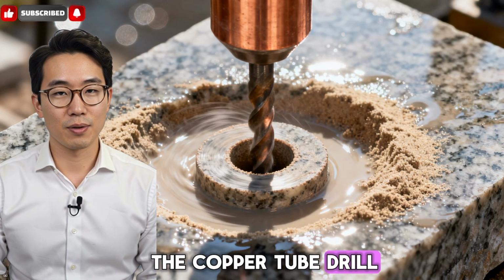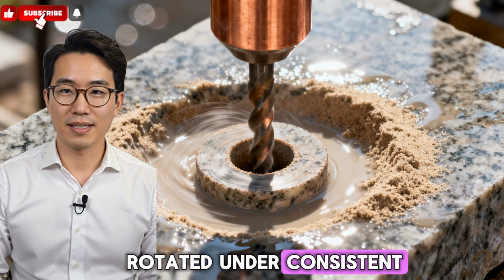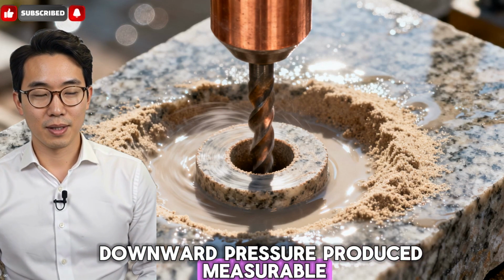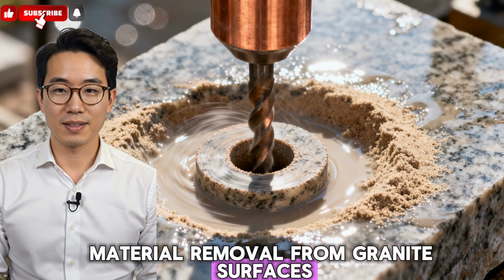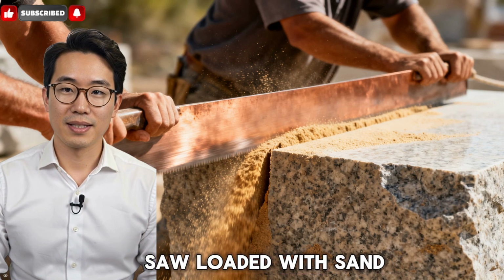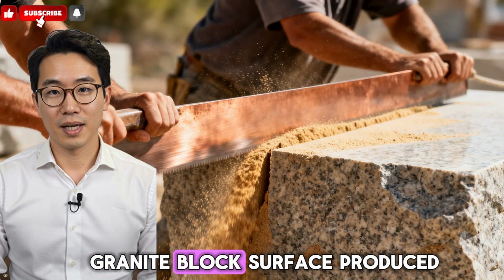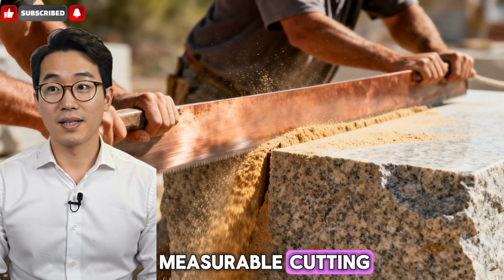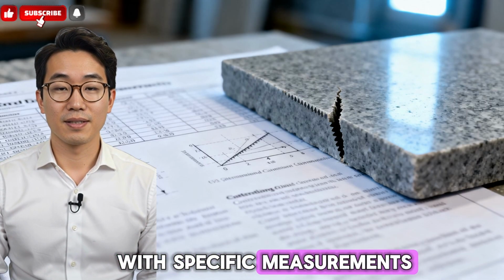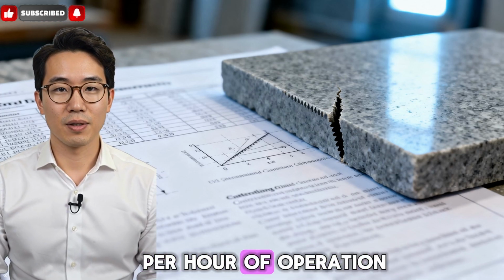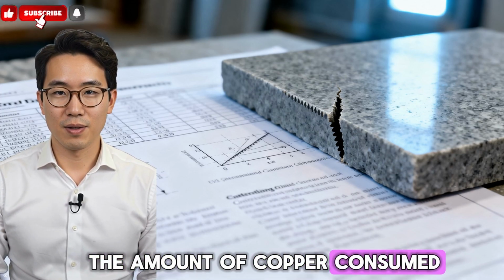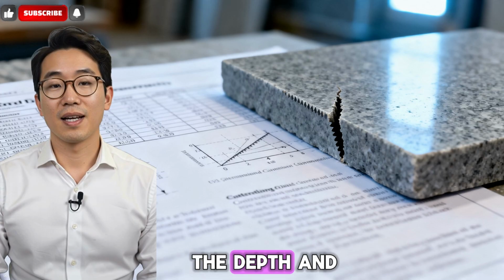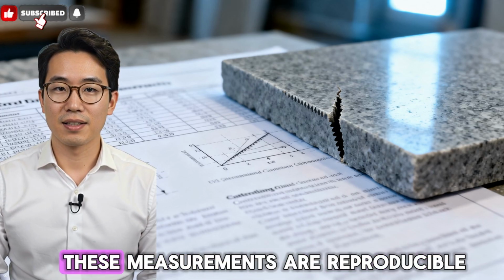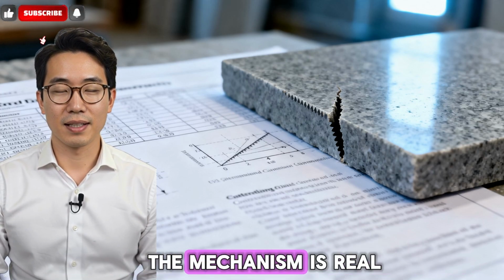The copper tube drill, loaded with quartz sand and rotated under consistent downward pressure, produced measurable material removal from granite surfaces. The copper flat-bladed saw, loaded with sand and moved back and forth across a granite block surface, produced measurable cutting. The results were published with specific measurements: the rate of material removal per hour of operation, the amount of copper consumed per unit of granite removed, the depth and character of the cut surface. These measurements are reproducible. The mechanism is real.